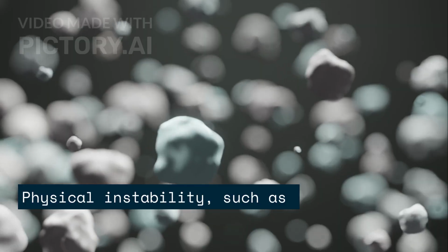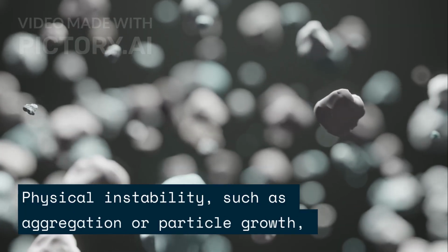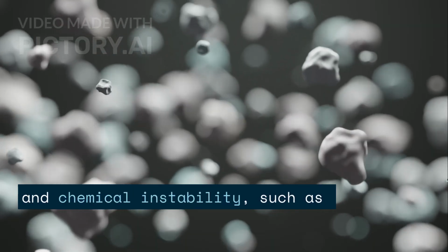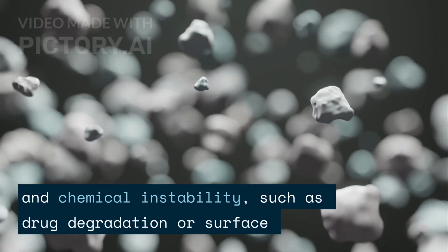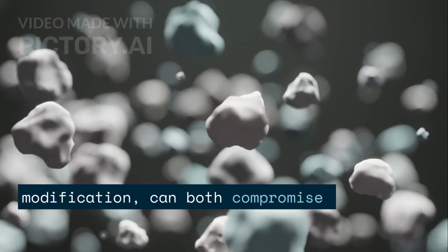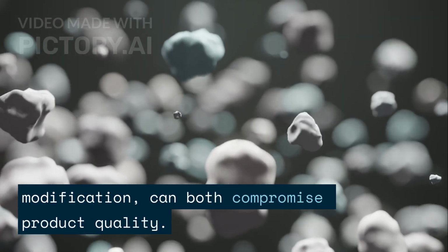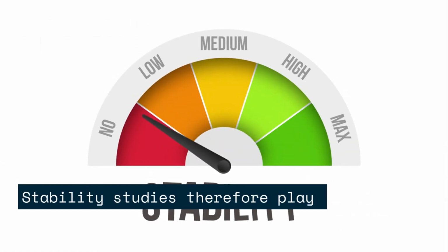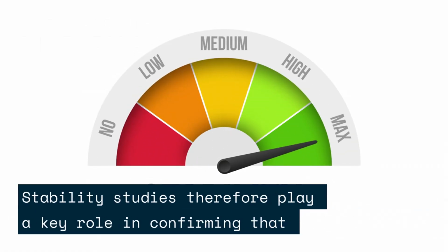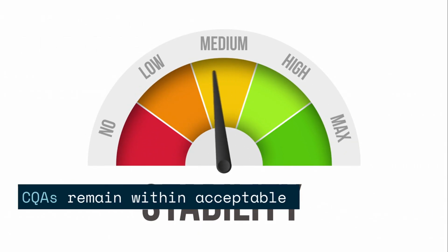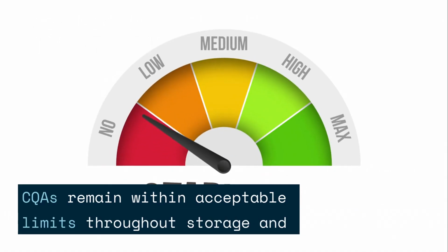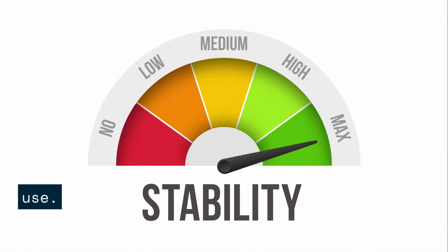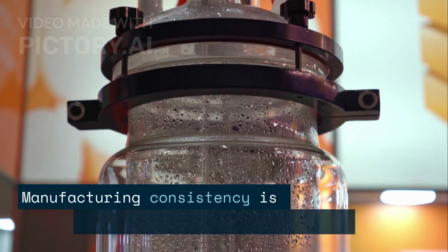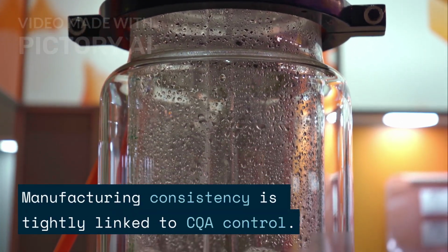Physical instability, such as aggregation or particle growth, and chemical instability, such as drug degradation or surface modification, can both compromise product quality. Stability studies therefore play a key role in confirming that CQAs remain within acceptable limits throughout storage and use. Manufacturing consistency is tightly linked to CQA control.